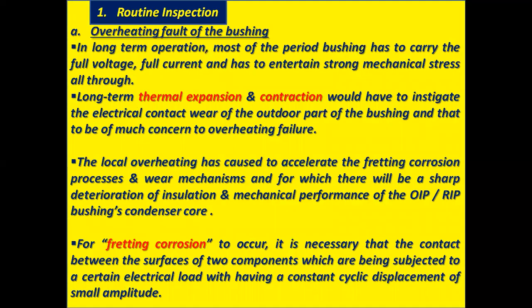1. Routine inspection. A. Overheating fault of the bushing. In long-term operation, most of the period, the bushing has to carry the full voltage, full current, and has to endure strong mechanical stress all through. Long-term thermal expansion and contraction would instigate electrical contact wear of the outdoor part of the bushing, and that is of much concern for overheating failure.